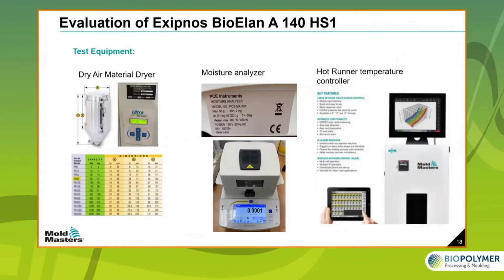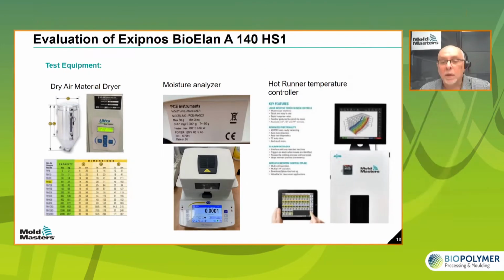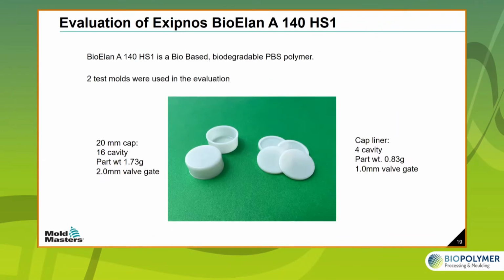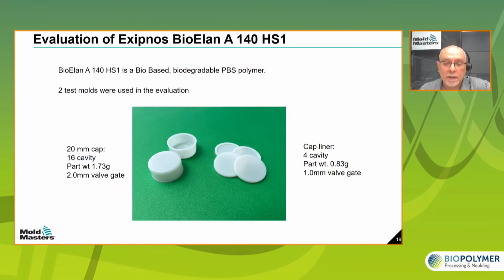Part of the evaluation equipment, material needs to be dried. So we have a dryer on our machine. After we have dried it for the specified time and temperature, we can do a moisture analysis to see how much moisture there is in that material. And then the other part is the hot runner system and control, a temperature controller to control the hot runner system. Our previous mold evaluation or material evaluation used the closure you see on the left-hand side. This is our 20 millimeter closure. In addition, we have another part that is a cap liner.